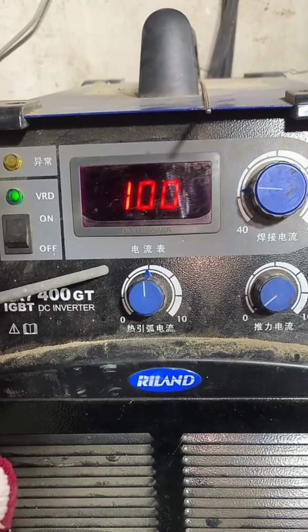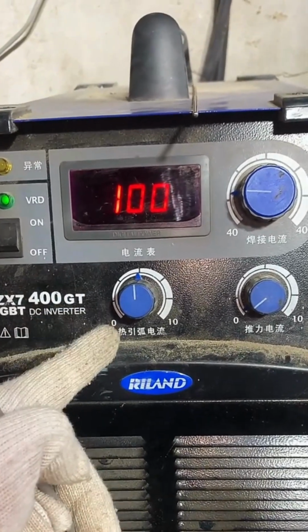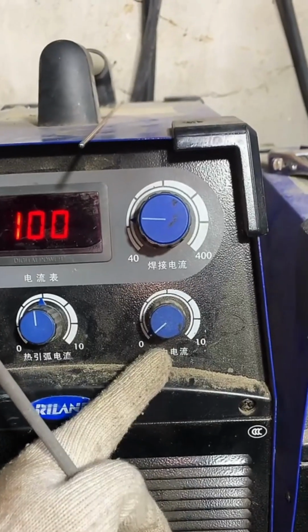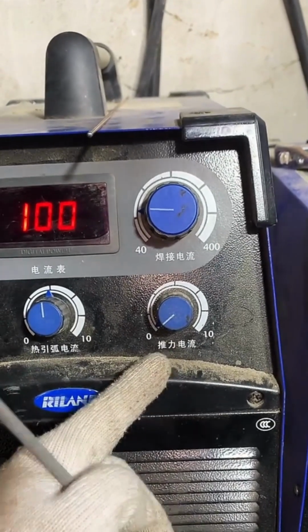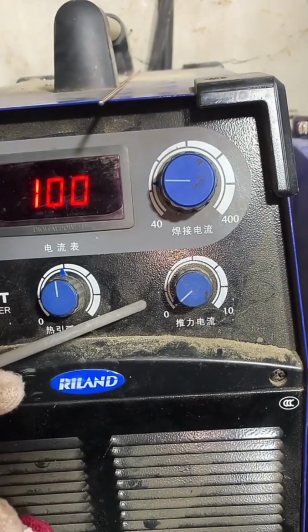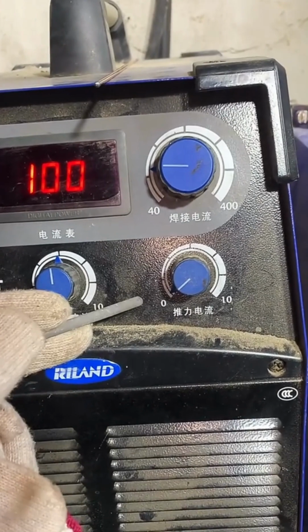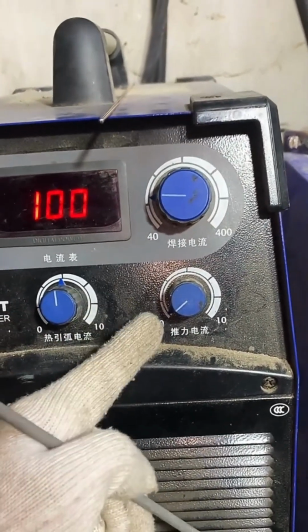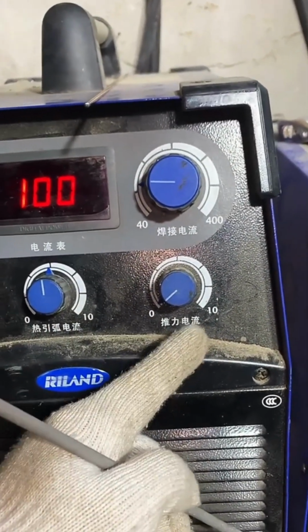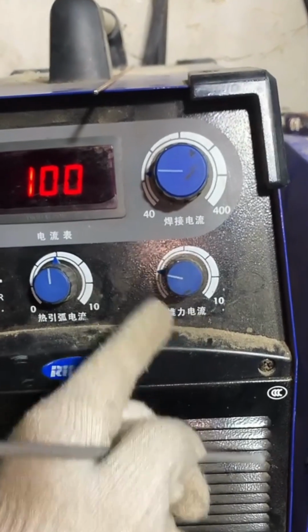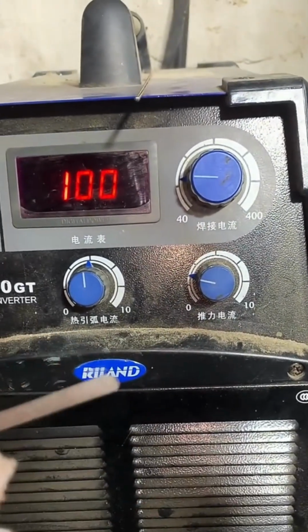The electrode and the workpiece are quickly short-circuited. The current is 100. It won't stick anymore. If sticky strips appear during the welding process, the electrode voltage is too low due to the small current. When the arc voltage is less than 15 volts, we can add a little thrust of the current.